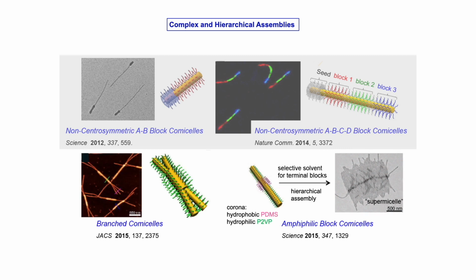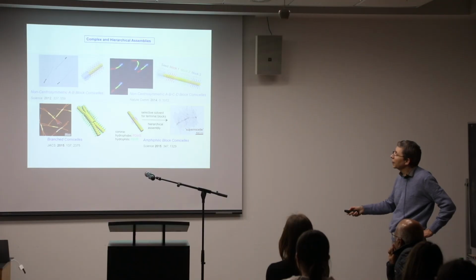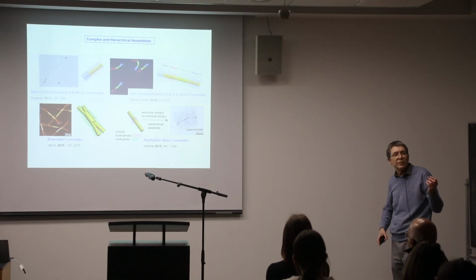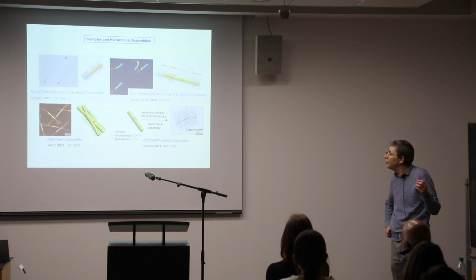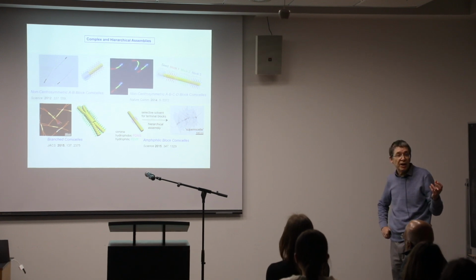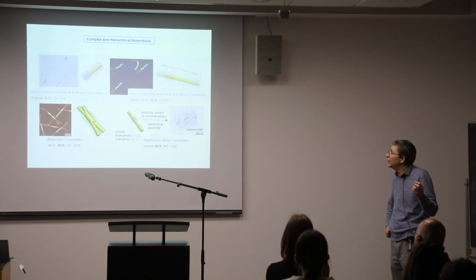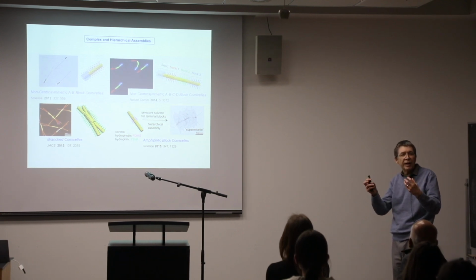You can make branch structures, as we've shown here. You could also make these structures so they themselves will self-assemble into micelles, where the middle is hydrophobic and the ends are hydrophilic. This is just like one of the amphiphilic surfactants or amphiphilic block copolymers I showed you earlier, in that because there's a polar end and a non-polar end, these will self-assemble in solvents that are selective for one of the blocks.